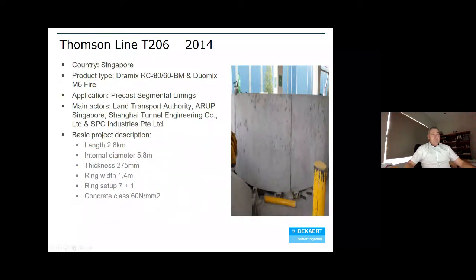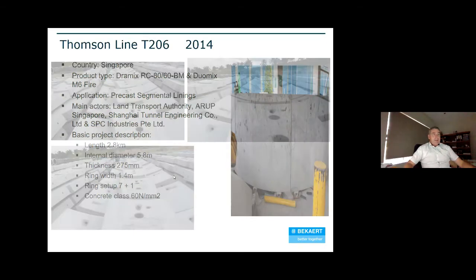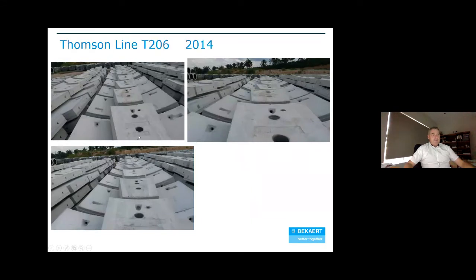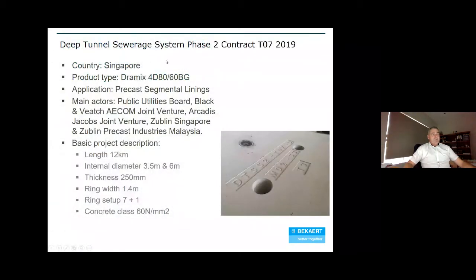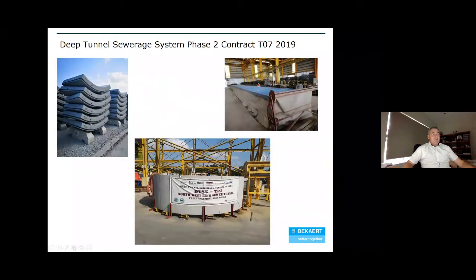Another project is the Thomson Line 2 T206, which was done in 2014. Again, a 5.8 metre tunnel. Those are some photos of the segments, and you can see how there are absolutely no fibres on the surface at all in any of the photos. A more recent project, which is always really interesting, is a deep sewer tunnel in Singapore, where we're currently supplying 3.5 metre and 6 metre internal diameter. Again, you can see very little to no vision of any fibres on the surface. And just a couple more photos from that project.